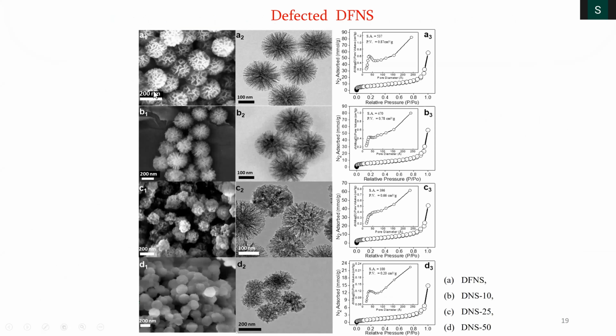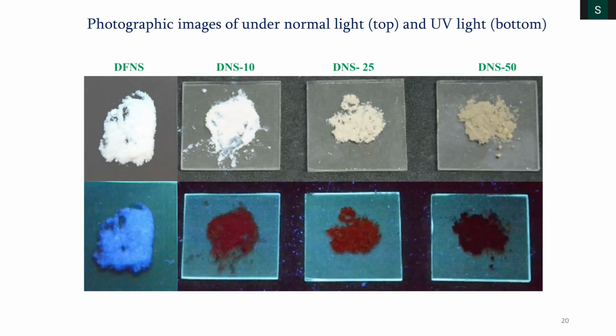This is a normal preliminary characterization indicating that the morphologies remain nearly intact. Maybe at higher loading there is some loss, and the surface area is also okay. Maybe at higher concentration of magnesium the surface area reduced to 100, but still it is not a bad surface area. This is a typical imaging, normal light and UV light, indicating that there could be defect sites which are emitting different wavelengths of light.